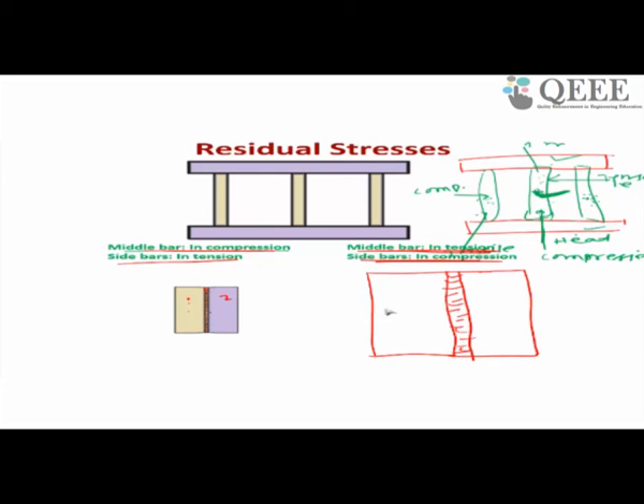This is the welding zone. What kind of stress field will be created? Suppose this is the axis, you will get something. If this is tensile and this is compressive, you get this kind of stress field. So in the welding zone, you will get a high level of tensile stress field, and an internal stress will be developed, and away from the welding, you will get a compressive stress field. That's why this is called residual stress.